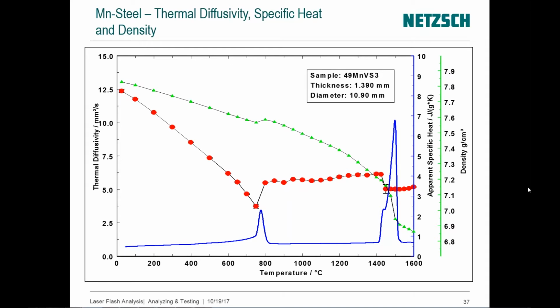Another question is, how do we measure the signal from the detector, or do we actually measure the temperature? Two things are very important. We indeed do not measure the temperature, or we could if we calibrated the detector. It is important to know that in that case we don't really use a calibrated sensor. The detector is not necessarily calibrated. We can if we want to, but we don't.